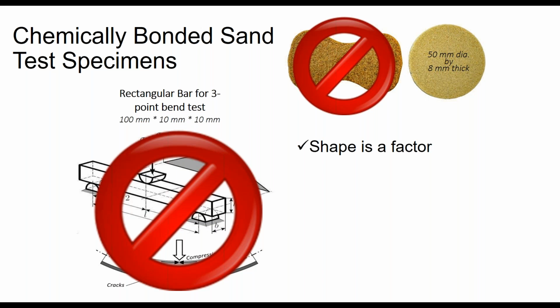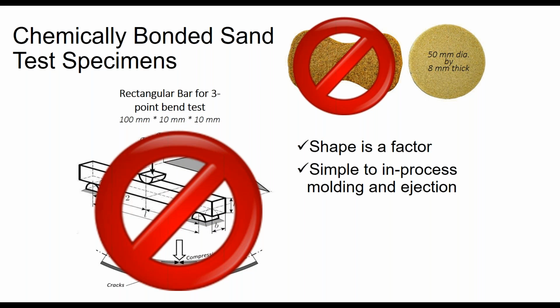If we now go beyond mechanics to look at what is really happening in a metal casting process, thermomechanically, thermochemically, thermophysically, if we take a simple shape like a disc-shaped specimen, we can wet it, we can learn more. The shape is simple, we can build it in our process and not have any residual stress in ejecting it from our tooling. And then the heat transfer factor. Again, the shape factor is simple. If we put heat at the bullseye of our specimen, we know where that heat will go radially and axially.